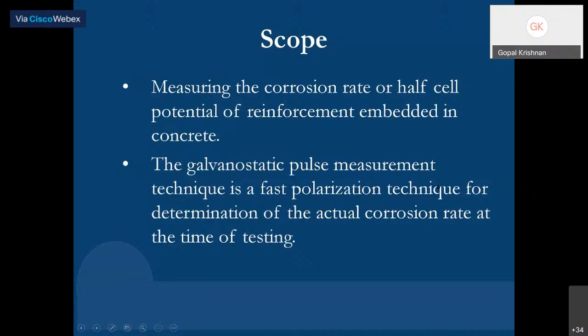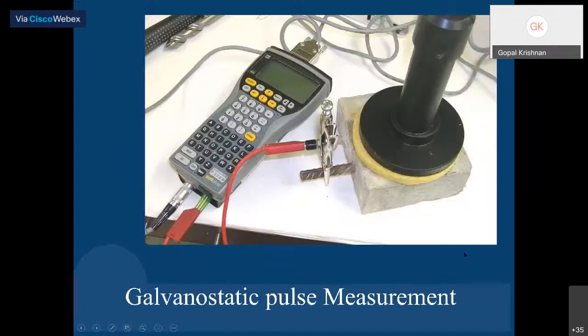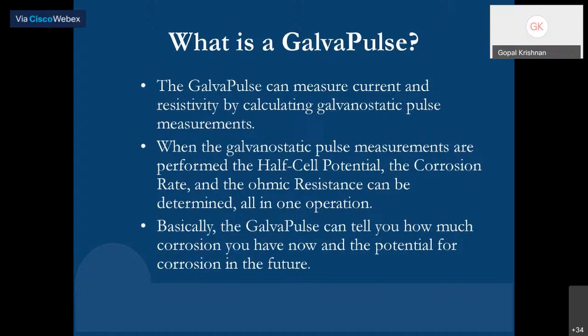The GalvaPulse measurement technique is a fast polarization technique for determining the actual corrosion rate at the time of the test, so you can say real-time readings. The instrument looks like this, with the probe and a handheld computer, which calculates the resistivity, the rate of corrosion, as well as half-cell potential readings. It measures current and resistivity by galvanostatic pulse measurement.